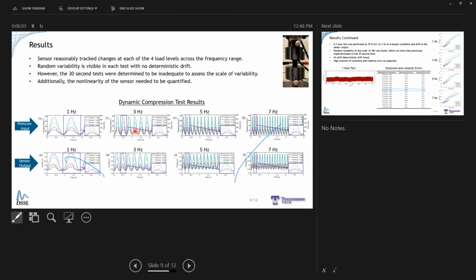What we found was that the sensor was able to track the load levels and frequencies reasonably well. However, we did notice that there was variability in these signals. So we decided that these shorter 30-second tests were inadequate to determine the variability of the sensor. And also we wanted to be able to quantify the nonlinearity.